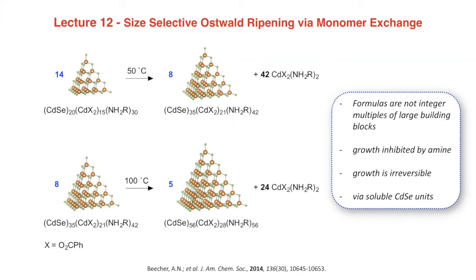They are small enough that the volume available to ligands around those pyramids is about 2 to 3 times higher than a flat surface. So the ligand packing here helps to stabilize these particular clusters. And that is possible because of the small size and the high curvature.